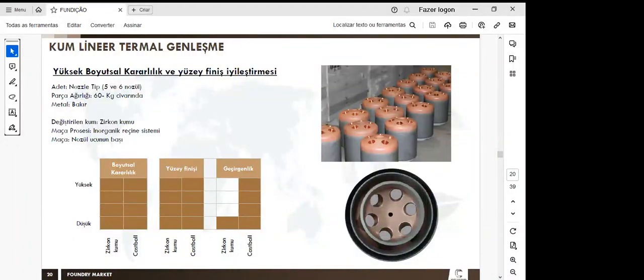And the last case that we show you, Castball replaced zircon sand. This piece is a nozzle tip, a copper metal casting. With Castball, the casting presents high dimensional stability, excellent surface finish, and greater permeability. In other words, the piece produced with Castball presents similar results to pieces produced with zircon, but at lower cost.